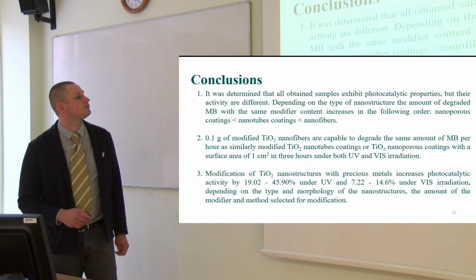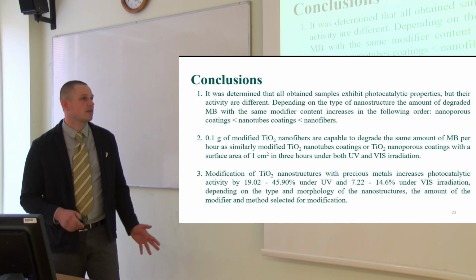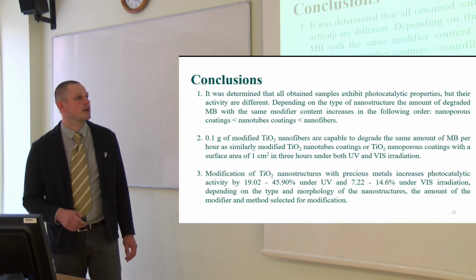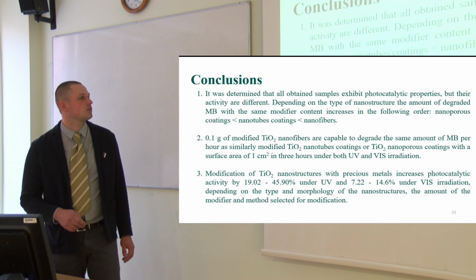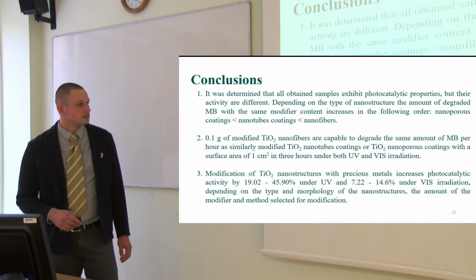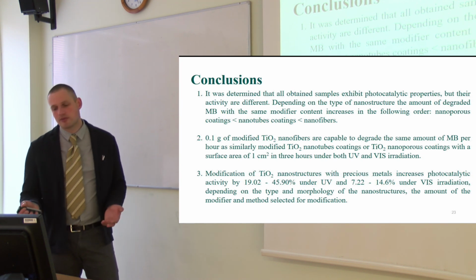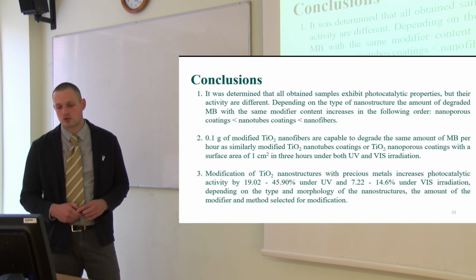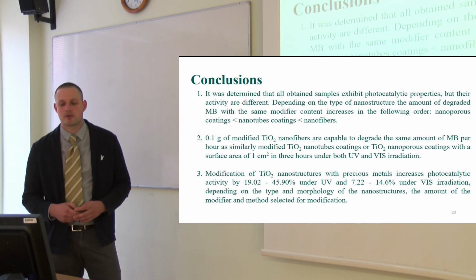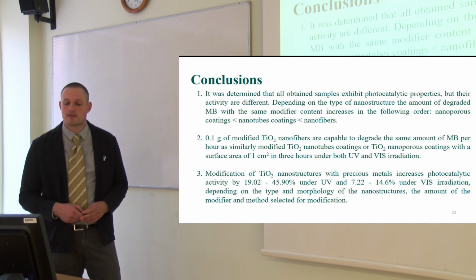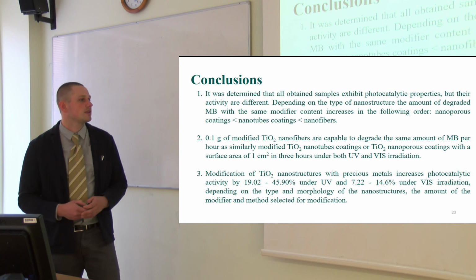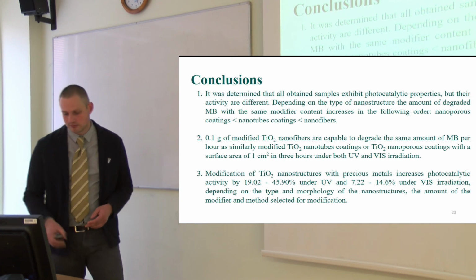So some conclusions. The main one is that if you have samples with the same modificator amount, the activity increases in the following order: nanoporous coatings, then nanotubes, and then nanofibers. And if we compare nanofibers with nanoporous and nanotube coating samples, then it was noticed that 0.1 gram of modified titanium dioxide nanofibers can degrade the same amount of methylene blue per hour as similarly modified titanium dioxide nanotubes or nanoporous coatings with surface area 1 square centimeter in a 3 hour experiment.